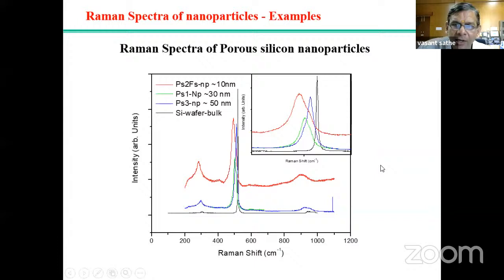If it is a nanoparticle, you see for a bulk, Raman is coming at a very sharp and Lorentzian type of line shape. While if you go to nanoparticles, as the size is reducing, it is getting redshifted. Redshifted means the frequency is getting lowered or the wavelength is getting higher, and it is getting broadened and asymmetric. So that is the fundamental difference. So for characterization of nanoparticles, you can do it. And all these spectra are recorded in a few minutes. Believe me, this is in a few minutes.